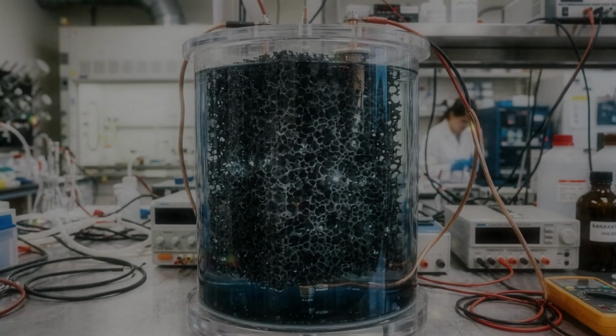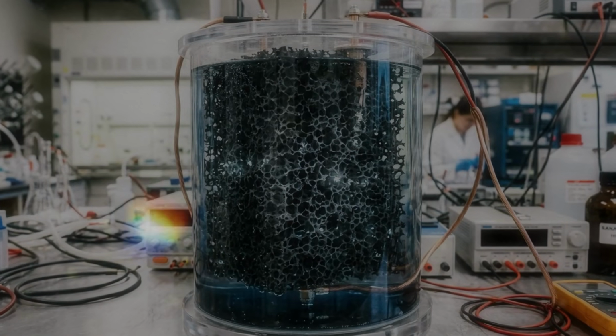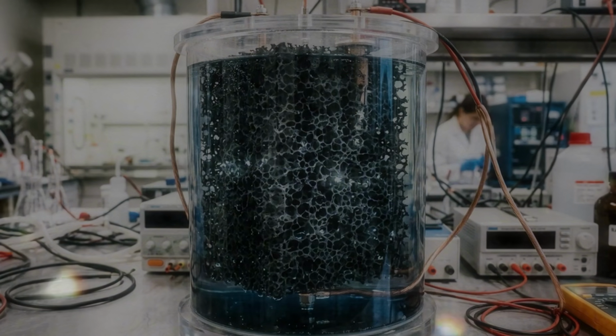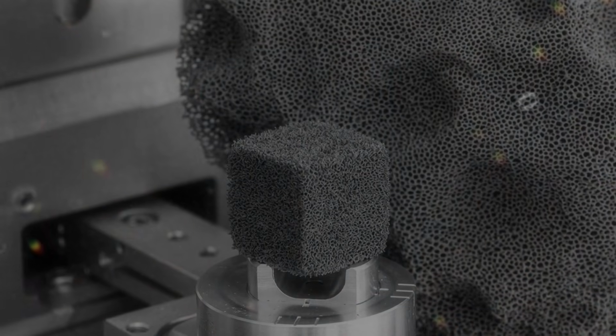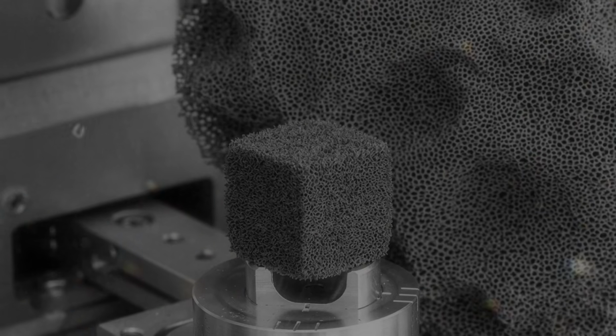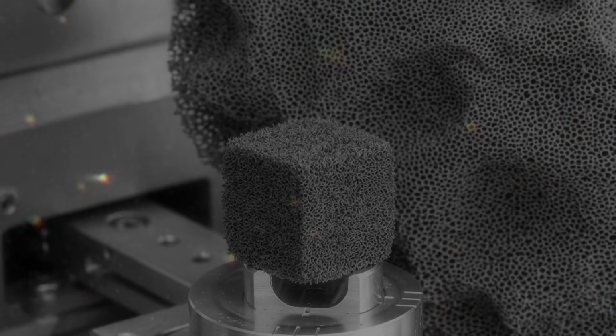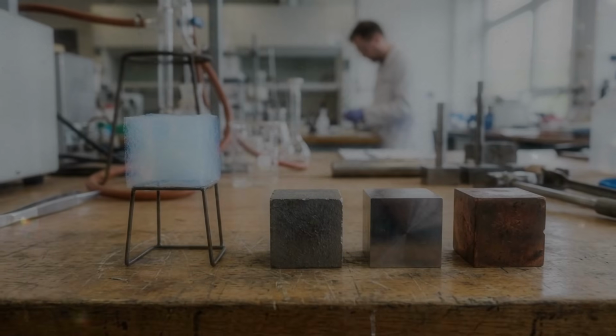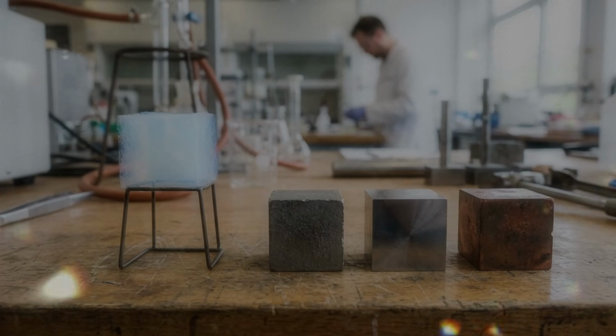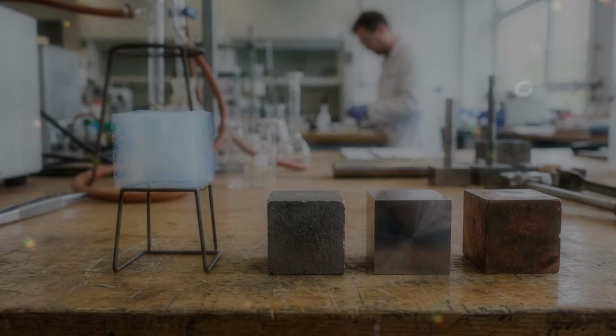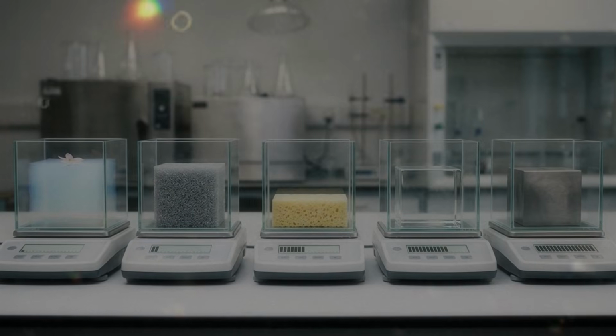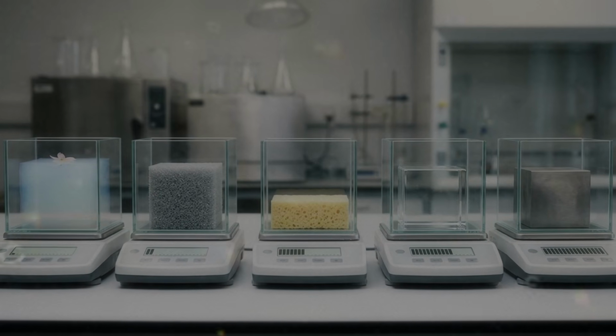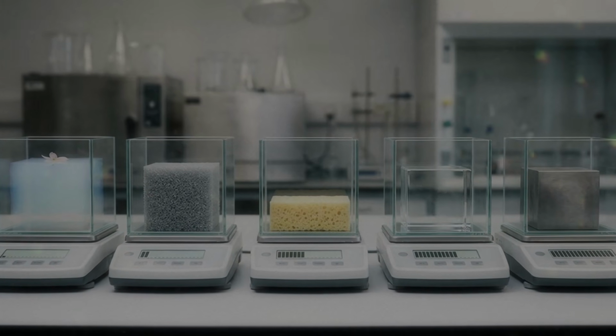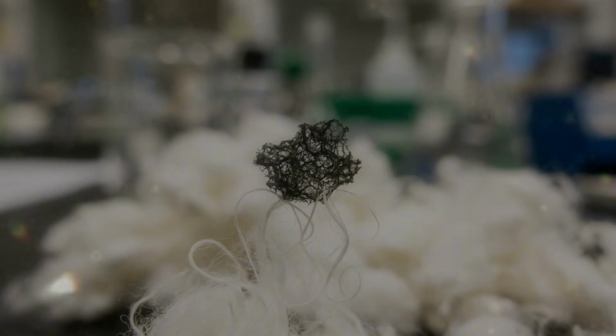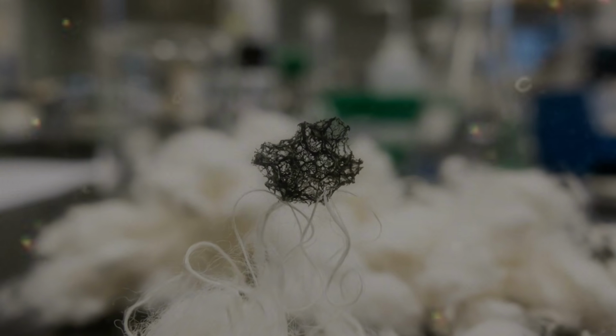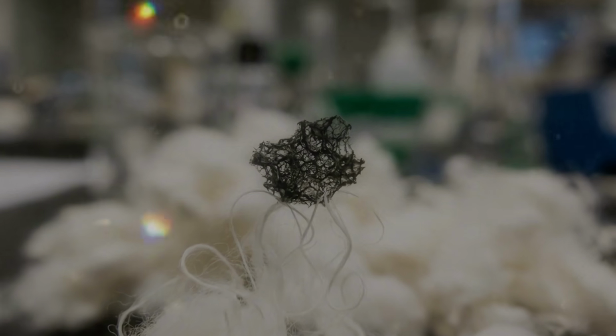By adding oxygen-containing groups, researchers make the sheets more compatible with water. They can be stirred or treated with sound until they spread through the liquid. The result may resemble a dark brown or black suspension. Each sheet is extremely thin, but there can be enormous numbers of them drifting through the container. The sheets must then be encouraged to connect into a three-dimensional network. This can happen through chemical reduction, heating, changes in acidity, added linking molecules, or interactions with polymers and other materials.